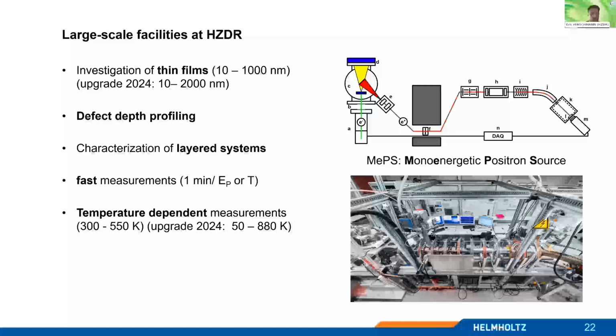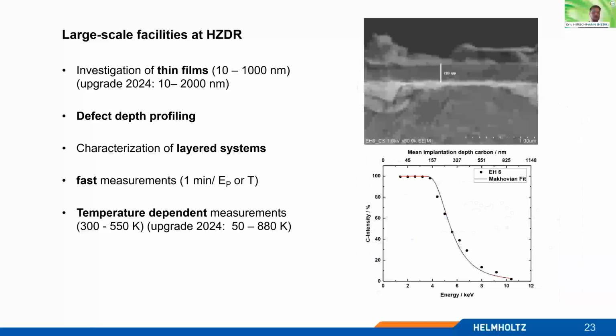And here you are a little bit faster, so 1 minute per energy or temperature, which at the moment can be varied from 300 to 550 Kelvin. We would like to upgrade this system at the end of this year, but to be honest, maybe the beginning of next year could be the good point. And then the temperature can be varied from 50 Kelvin to 880 Kelvin in situ for thin films. And I think this will be quite a huge change or upgrade for this kind of setup.